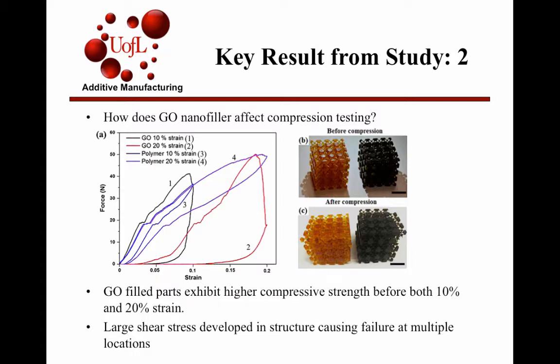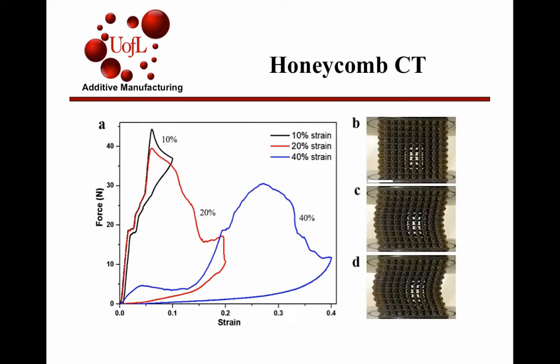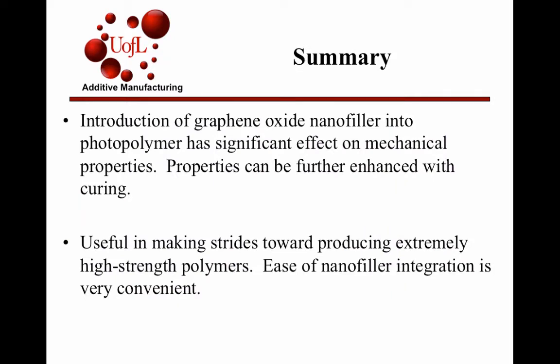Let's see. In summary, just like the hypothesis thought, the introduction of graphene oxide, and there were other papers done on just graphene by itself, but this one was specifically graphene oxide, did have a significant effect on mechanical properties of the polymer. And then another thing is that the properties can even be enhanced with curing. That was a big step as well.